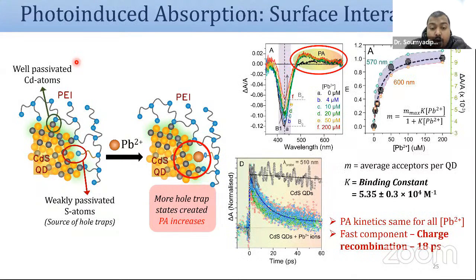which is the reason we have a more positive signal in the photoinduced absorption. Okay. Now, if we see this particular adsorption of lead 2+ at the surface, you can plot the kind of isotherm, and it gives you the binding constant around 10⁴, which is kind of agreeable with the literature constants. So, what is actually happening?